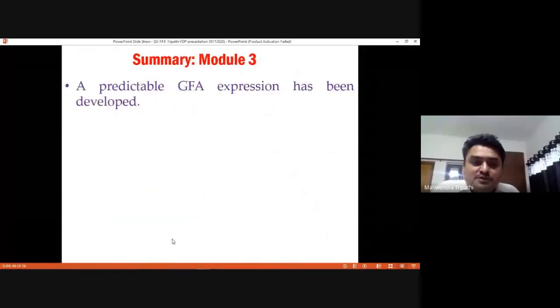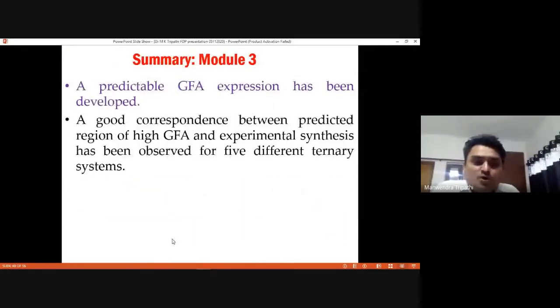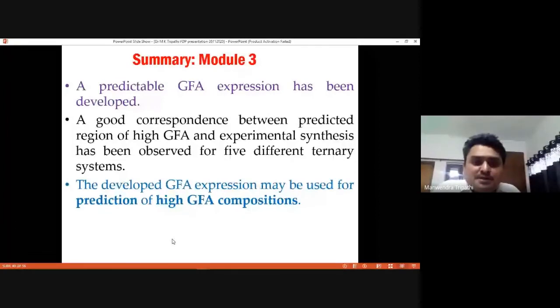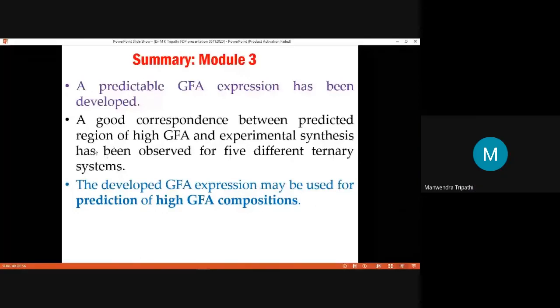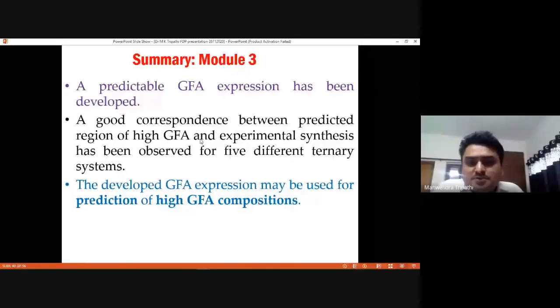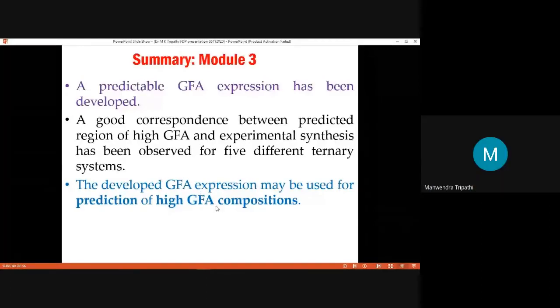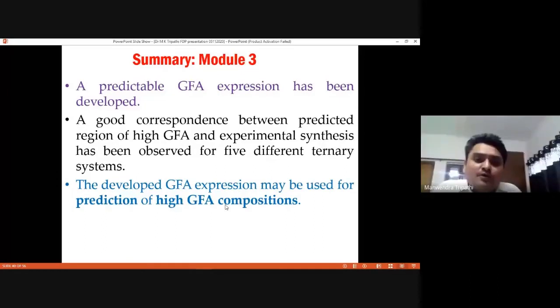So the summary of module 3 is that the predictable GFA expression has been developed. A good correspondence between the predicted region of high GFA and experimental synthesis has been observed for 5 different ternary systems, and the developed GFA expression may be used for prediction of high GFA compositions. And for details you can refer to this paper in Intermetallics.